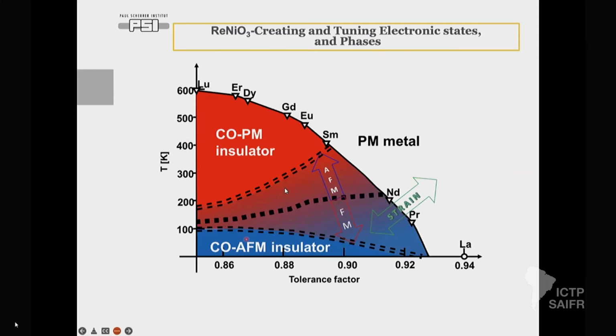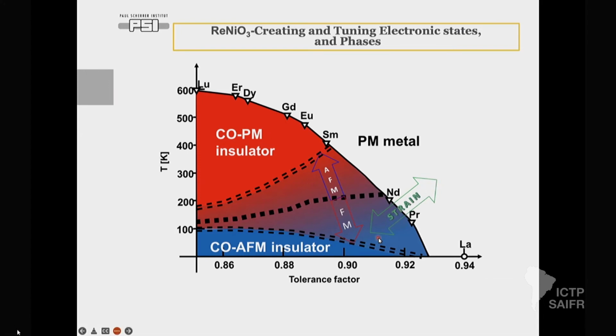And if you see now, this is the phase diagram which I showed before, a bit simplified. The strain basically moves the system to be more metallic, or paramagnetic metallic, or insulator. So you are able to move that line in and out, because you are changing the tolerance factor by the heteroepitaxial strain. But why are we not trying to do something more, to also change this magnetic line and separation line?